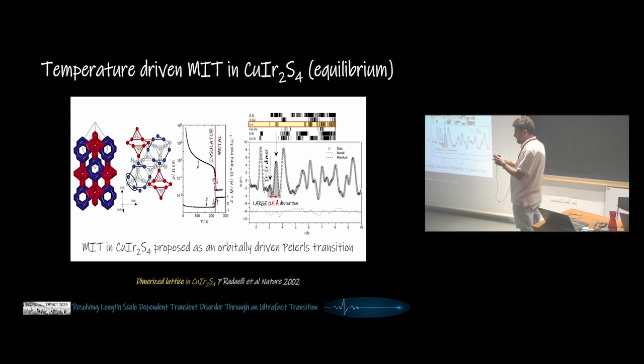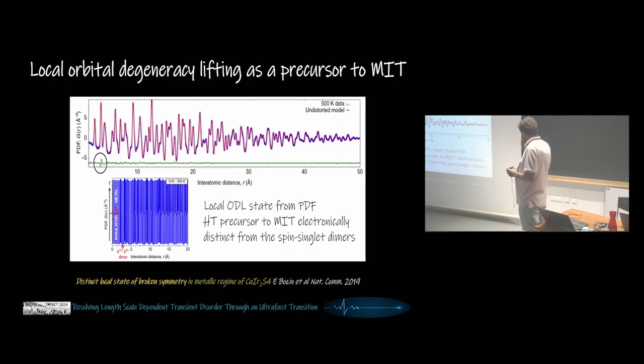So the short dimer bond appears as a new peak here, which is very well resolved from the principal iridium peak in the undistorted matter. This is this big guy here. Okay, so the transition in equilibrium is proposed to be an orbital Peierls transition. We have studied this system with PDF some time ago, and so here you see a stack of PDFs as a function of temperature as you go from the low-temperature dimerized to the high-temperature cubic regime.